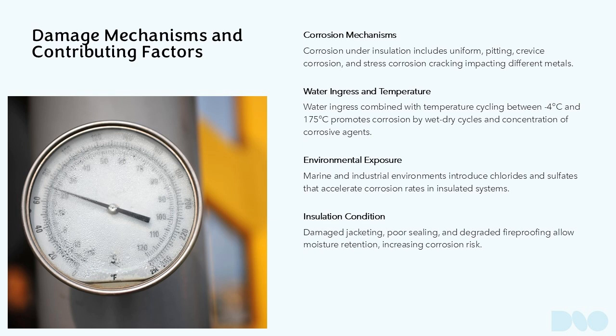These mechanisms are accelerated when insulation systems absorb and retain water, creating persistent wet conditions at the metal surface. Key contributing factors include water ingress from rain, washdowns, condensation, or process leaks, combined with temperature ranges that promote evaporation and concentration of corrosive species. Certain temperature bands, typically between approximately -4 degrees Celsius and 175 degrees Celsius, are especially conducive to CUI due to repeated wet-dry cycles. The type and condition of insulation or fireproofing material also play a significant role.